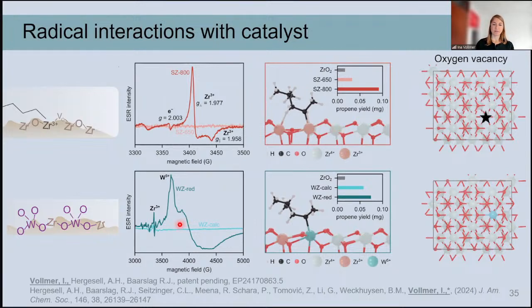And we then also tried another material, which is this tungstated zirconia. And there you can create two different materials by either reducing the material, and then you have a lot of unpaired electrons with this tungsten 5+, and also zirconium 3+ increases in intensity, while just the prepared and calcined materials doesn't have that many unpaired electrons. And here we also see the difference in the stabilization of the radicals of the two materials.